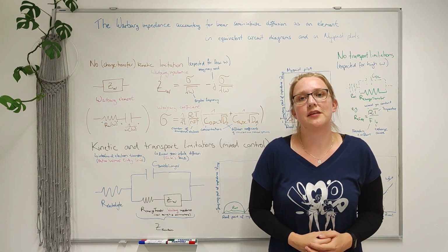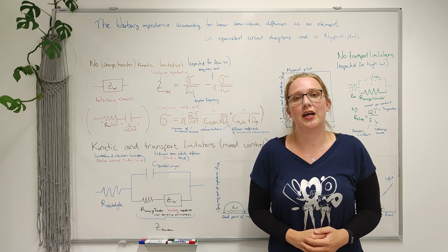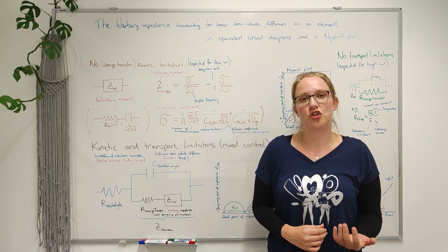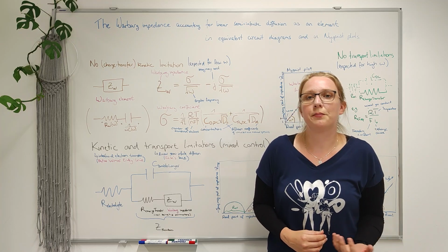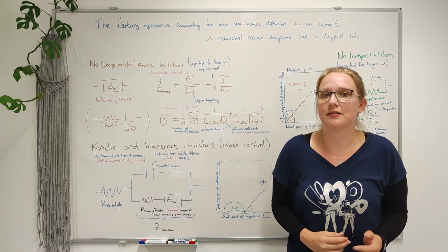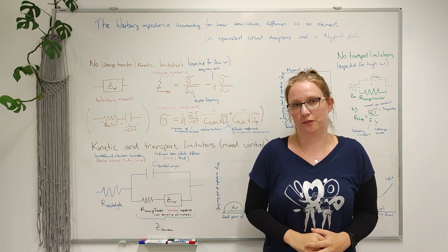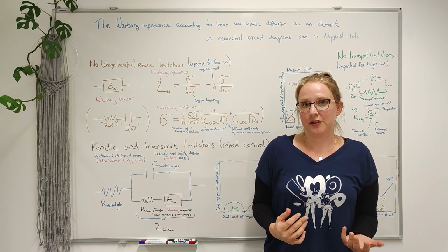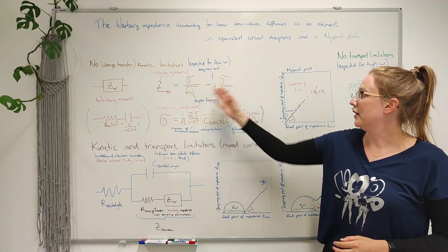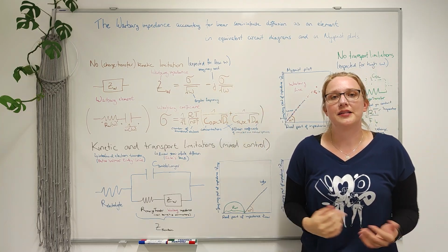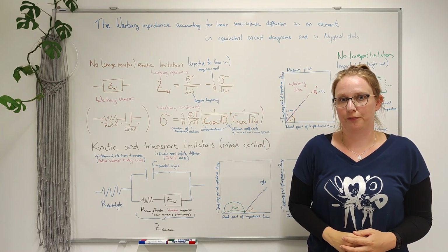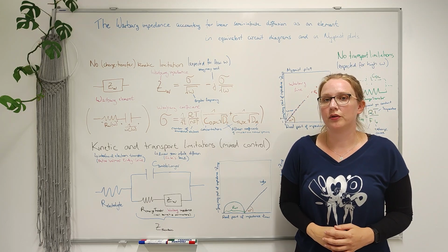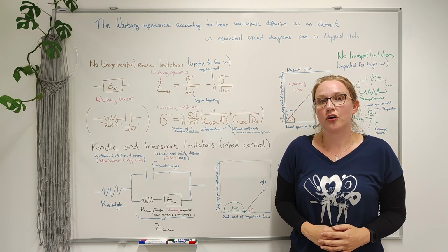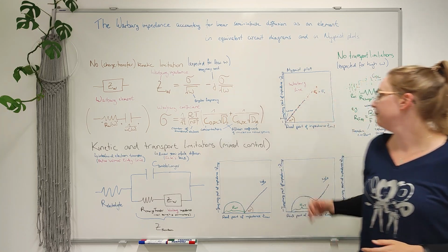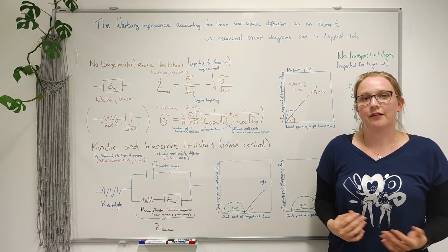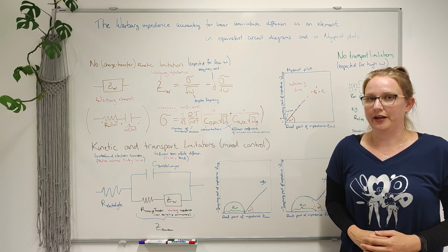Thinking about it in this way is somewhat closer to Emil Warburg's original idea of describing periodic concentration changes at the electrode, which disappear with great distance from the electrode, as a capacitance of polarization. As we can see, both the real and the imaginary part depend on the square root of the angular frequency. Further, both impedance components are of equal value, and accordingly plotting in the complex plane gives a straight line with a slope of 1, which we call the Warburg line.